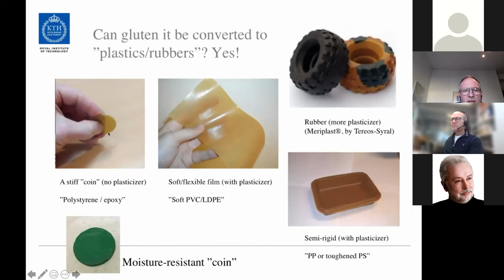If you don't use a plasticizer, you'll have a stiff and brittle material. If you put plasticizer in it, you have PVC-like or LDPE-like properties, and that's when you have a relatively large amount of plasticizer. For a medium amount of plasticizer, you can make semi-rigid trays, for example. Here are some wheels actually produced with wheat gluten. The moisture issues can be dealt with by coating, with a paint, for example. This coin here to the lower left is completely moisture resistant. It sustains water as well as very high relative humidity.